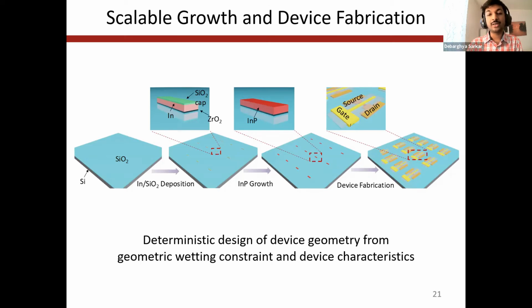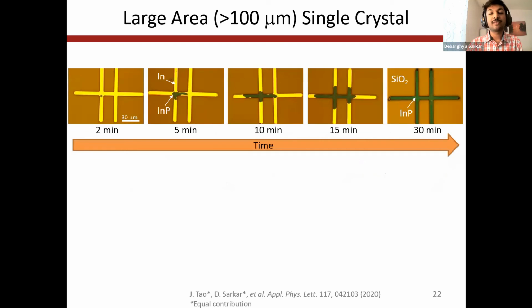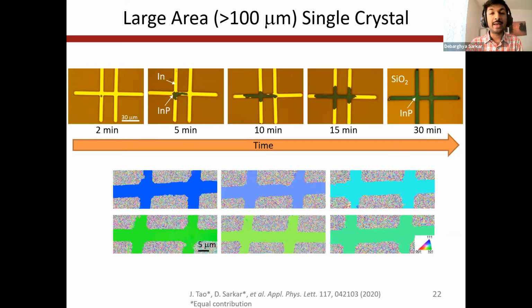For example, here we have grown indium phosphide single crystals with lengths exceeding 100 micron and widths of 5 micron. And the fact that these indeed are single crystalline is evidenced by this technique called electron backscatter diffraction, where essentially individual colors represent a single crystal orientation. So the fact that each of these 6 devices has the same color throughout indicates that they are indeed single crystalline.